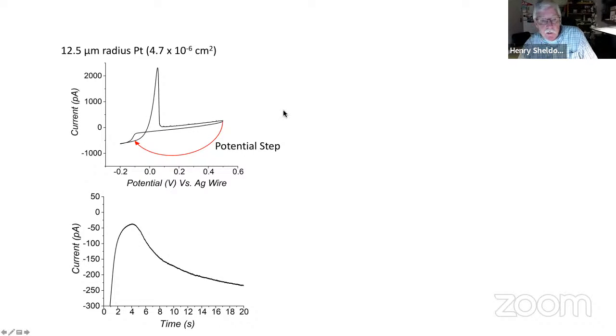So the classical way people study nucleation, kinetics of nucleation, is by potential step experiments. And so you step the potential where there's no metal deposition out to a negative potential where you're reducing the silver ion, and you record a current that looks something like this. This is double layer charging, the charging current decreasing, and then somewhere in this range here, you're starting to nucleate particles. They're starting to grow, so the current goes back up. This is a well-known response function.